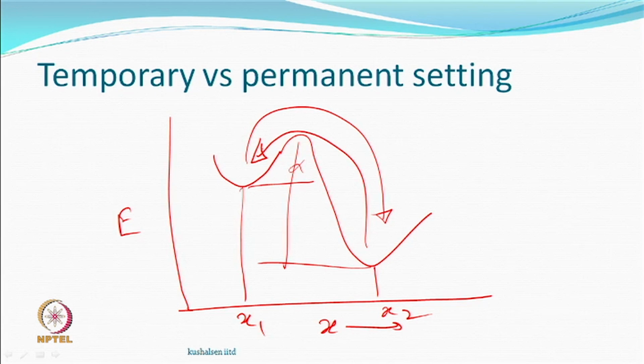temporary set. Like, let us say tomorrow you have a textured yarn itself, which is a beautiful yarn, you have kept it in a package for 3 months. As you know, winding tension may be good enough to keep the fibre in a fully flat state, because 0.1 gram per denier is a very small amount of stress required to completely remove the crimps.